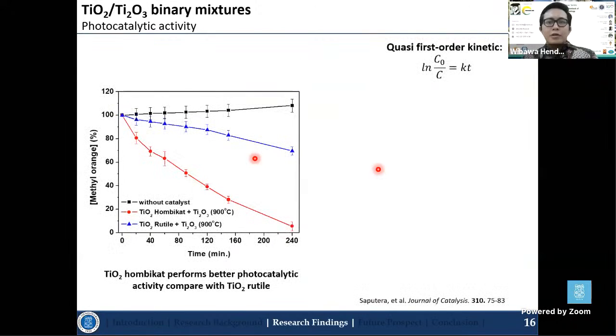So the reaction rate constants was then determined assuming the quasi first order kinetics using the following equations, where C0 is actually initial concentrations, the C is the concentrations of the dye at the time t, and the k is actually the rate constants. So it can be seen the red one is actually the anatase phase when mixed with the Ti2O3 or titanium trioxide, give the best performance compared with the rutile one. And also confirm that without using the catalyst, there is no degradations of the methyl orange appeared.